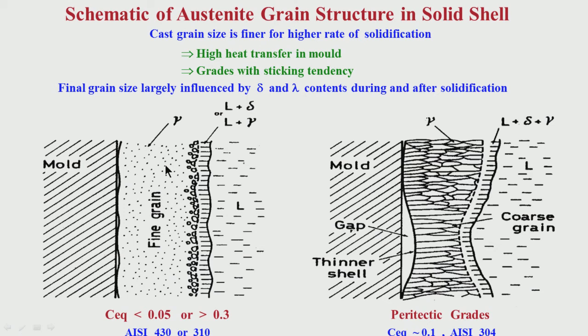So, the powder has to be such that the mold slag should have such characteristics that it can resist the friction, it can lower the friction between the mold and the solid shell. So, here friction is the issue, we have to take care of that. Here heat transfer is the issue which we have to take care of by using proper mold slag. So, as I was telling you, depending on the characteristic of the alloy, we have to use different casting parameters. We have to use different casting powder.